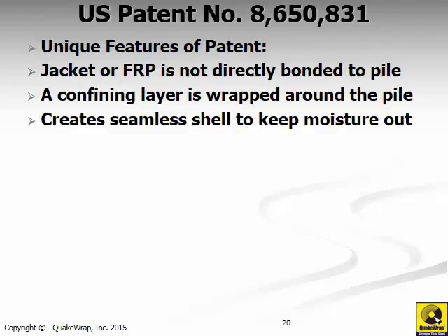And then a confining layer is wrapped around the pile, and this confining layer is what provides the confinement pressure for the column. That confining layer also creates a seamless shell to keep moisture out of the column, and as you know, moisture and oxygen are the fuel to the corrosion process. So by keeping the moisture and oxygen away from the column, we enhance the life of the column significantly.